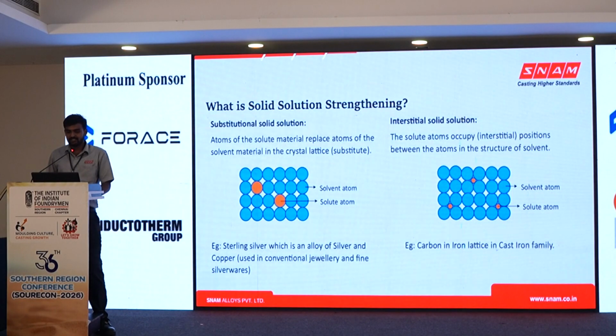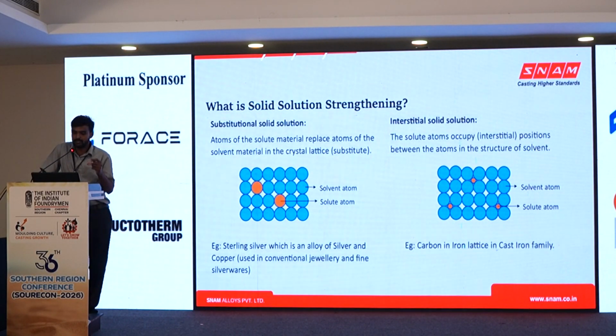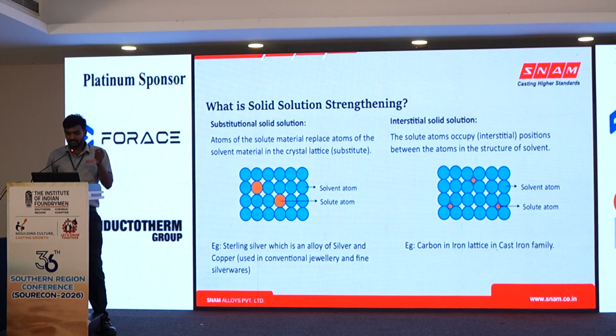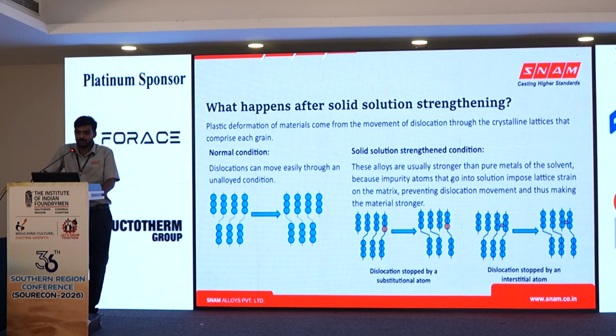But in the case of interstitial solid solutions, the solute atoms occupy the interstitial sites, the gaps between the solvent atoms. For example, carbon occupies the interstitial sites of iron. In steel and cast iron, you can see the carbon occupies the interstitial sites and increases the mechanical properties. So generally, what happens after solid solution strengthening?